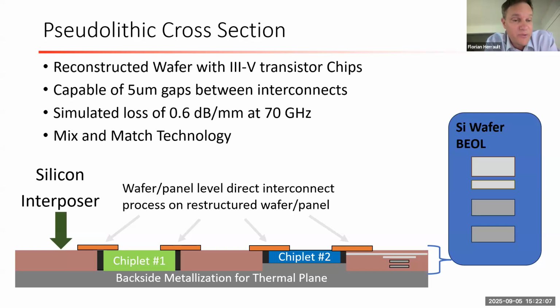The advantage of the dielectric bonding process is that it's very low cost, it's low parasitics at RF, and it allows us to run interconnects on the top directly from the chiplets to the silicon to electrically stitch the whole circuit together. So we have a wafer level process with gaps that can be as narrow as 5 microns, using an effectively redistribution layer type fabrication to interconnect the silicon interposer or silicon CMOS wafers with the chiplets. On the backside, we add a thermal backplane through a sputter and plating process, just like one would do in a MMIC level technology with the backside gold, for example, just to provide DC and RF ground as well as thermal management solutions as we interface to the package.